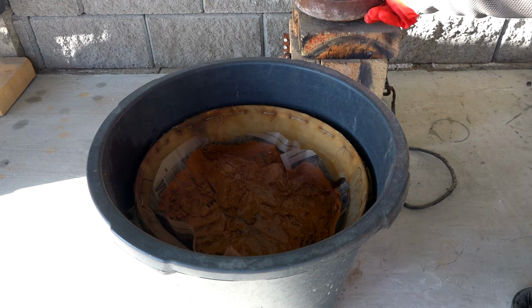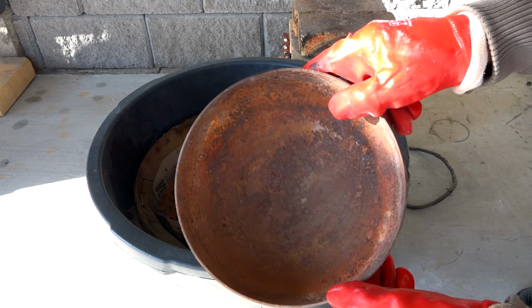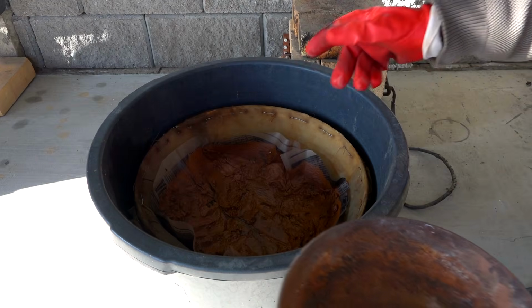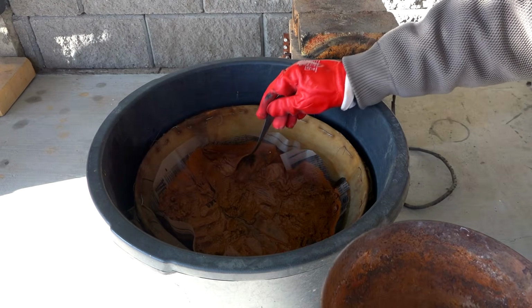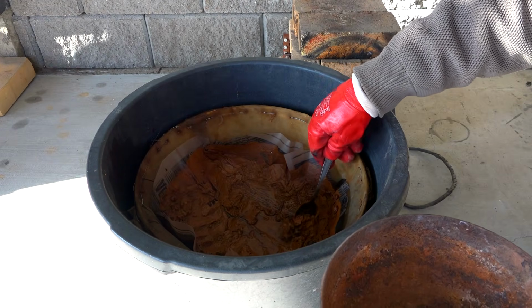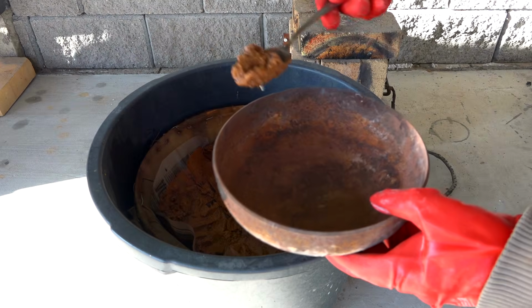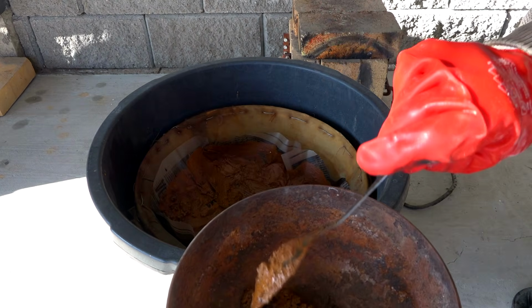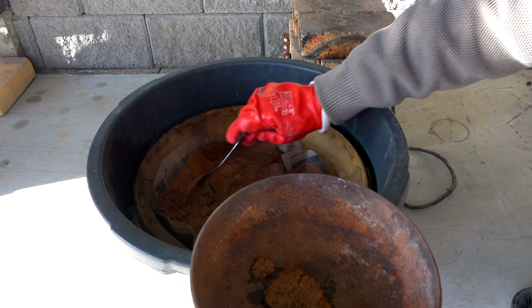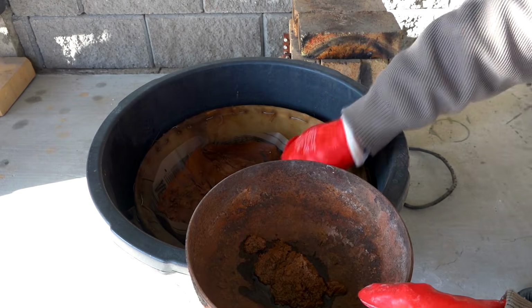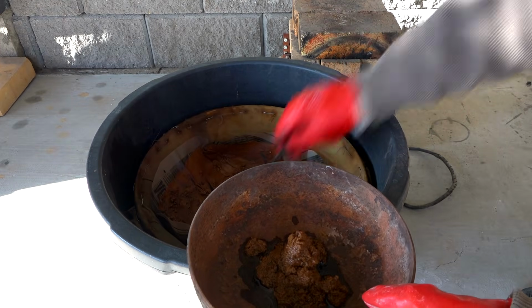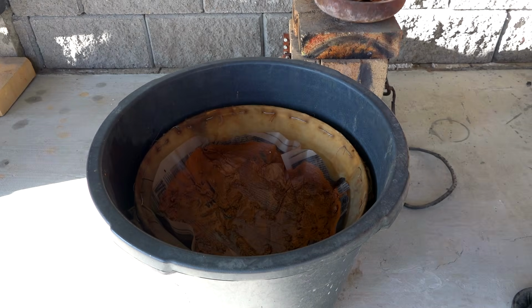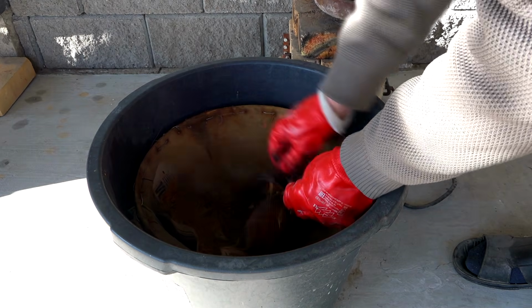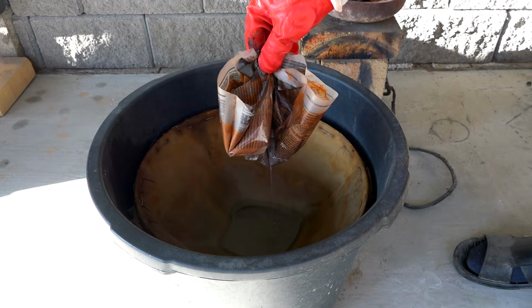Three days have passed since I began filtering the flotation concentrate. During this time, I have completely filtered the entire volume. Water and diesel fuel have seeped through the paper, leaving only a rich sediment. Now I need to transfer all the sediment to this stainless steel calcination bowl to remove any remaining diesel fuel. As you can see, after filtration, the sediment has compacted, and there is much less of it than initially.